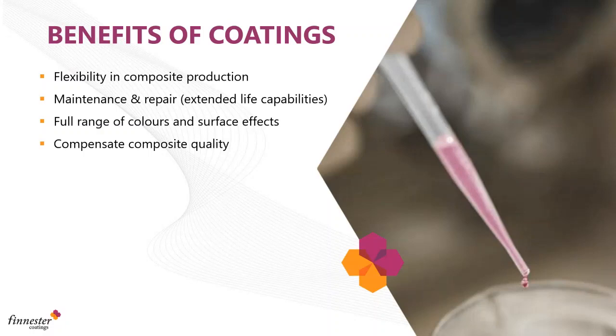You can extend their life, and you can repair them before they are actually broken. You can have a full range of colors and texture effects. You have different gloss levels. You can have different colors in different places. You are very versatile in the decorative options. And also you can compensate for some of the bad quality of the composite after demolding. Maybe there were some cracks in the gel coat, maybe there was some demolding pre-release, and you can repair those afterwards with the coating.